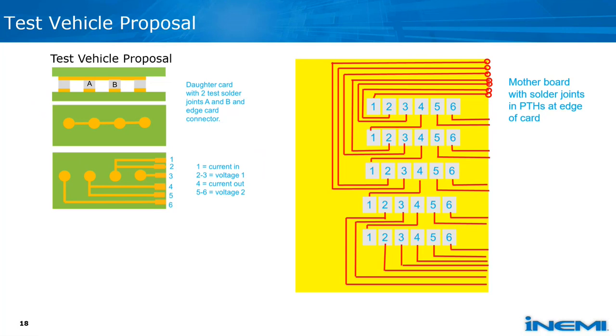Now that card edge connector will be inserted in a connector that is on the motherboard, that is shown on the right. And so you have 5 connectors on that motherboard, and you can insert up to 30 daughter cards, and then use that to measure the electromigration once you put it in the oven at specific temperatures. And you can also vary the amount of current going through some of these so that the current density can be varied.